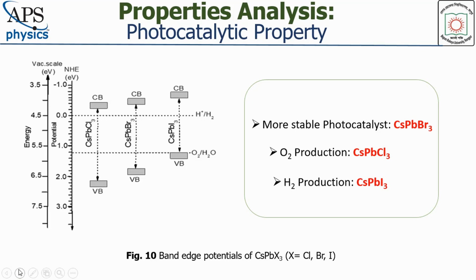these values, which implies that cesium lead chloride is suitable for oxygen production, which can be used as nanoparticle to refining water and to increase the oxygen level of polluted water of rivers. Cesium lead iodide is potential candidate for hydrogen production, which can play an important role in hydrogen fuel-based power plants.